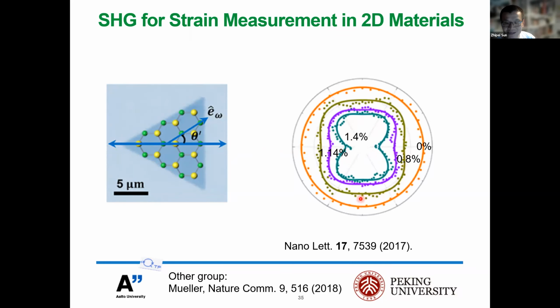You can clearly see here, we are able to detect the direction of the applied strain and also the amplitude of the strain in the flake. At the moment this is not possible with traditional optical methods. For example, with Raman and PL, we could only tell the strain amplitude, but not the strain direction. The physics behind this process is that when you apply strain along different directions of the 2D materials, the strain modifies the nonlinear response by the photoelastic effect. So using this effect, we are able to measure not only the strain direction, but also the strain amplitude.